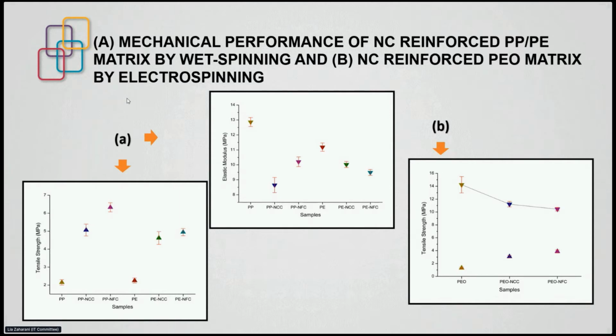Reinforced PEO matrix prepared by electrospinning. When we add some limited nanocrystalline cellulose to pure PEO, we clearly see the tensile strength increased. When we add nanofibrillated cellulose to pure PEO, we see the differences, which is nanofibrillated cellulose giving better performance than nanocrystalline cellulose reinforced PEO. In the other two samples, it is the same.